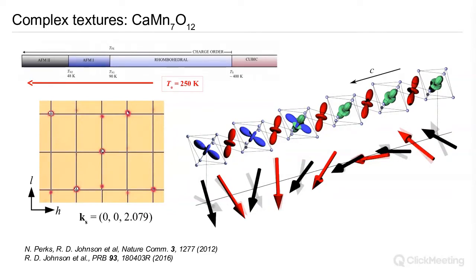In fact, the relative angle from one spin to the next is modulated throughout the crystal. And that phase, if you like, the angle between the spins, modulates with the same periodicity as the incommensurate orbital structure itself. So again, an interesting case that emerges from these perovskite families when we can play with the chemistry.